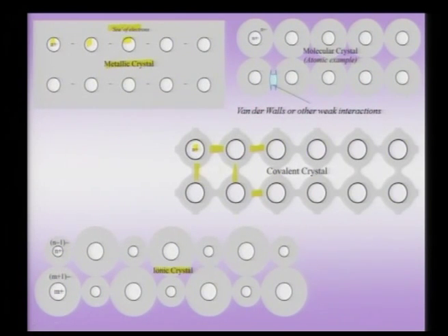That means electron density is not uniform, but it is also not localized; it is directed along the ion cores along certain directions. For instance, in the germanium or carbon diamond structure, you would notice that it is along the tetrahedral directions around a single carbon atom. So, that would be a covalent kind of crystal.